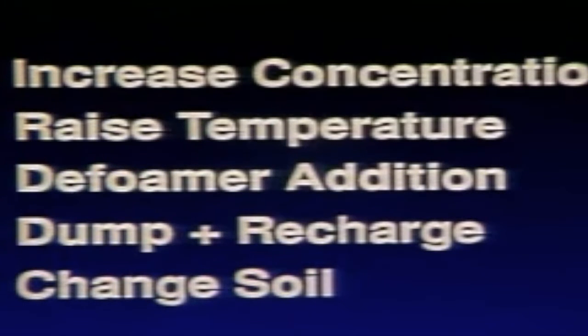The first would be to increase the concentration of the cleaner. By increasing the concentration, you increase the defoamer system to combat the increase in soil load. The second alternative would be to raise the temperature of the cleaning bath. By increasing the temperature, you help to increase the insolubility of the defoamer. This causes faster foam deactivation. The third alternative would be adding more defoamer. The use of a defoamer will combat foam by increasing the ability to control foam at greater concentration.